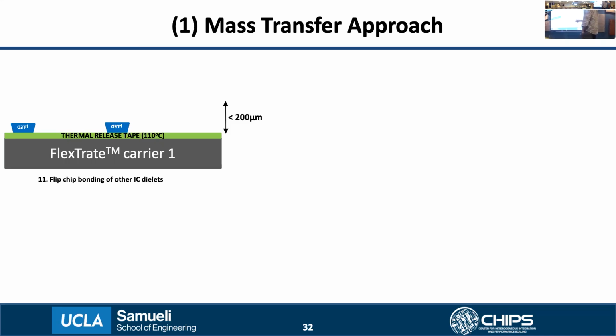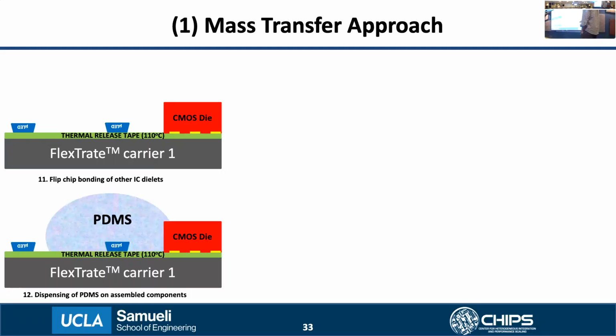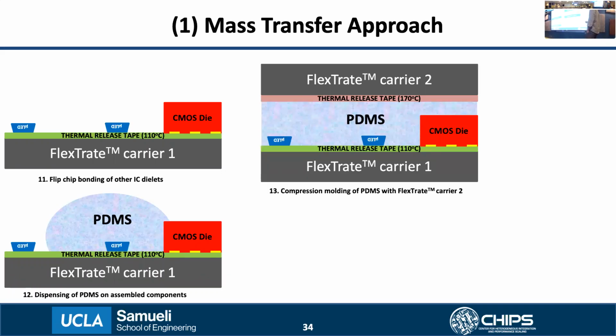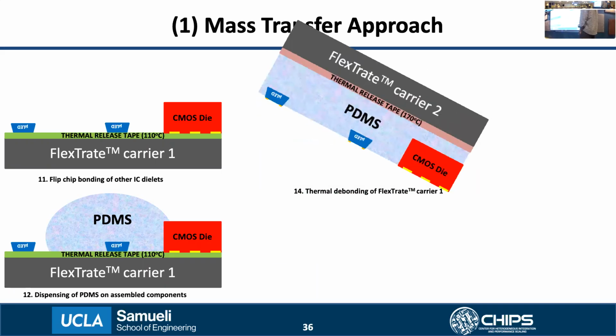And once all the LEDs have been fully assembled on the tape, we can then flip chip bond other components such as a CMOS driver die, a driver IC or a microcontroller. And then we do our fan-out process. In step 12, we dispense the PDMS, and in step 13, we compression mold the PDMS on these components using a second FlexTrate carrier with its own thermal release tape having a higher release temperature. We then thermally debond the first carrier so that we get this flat surface with the components embedded in the PDMS. And then we can do our RDL metallization using back-end line processing to define the two levels of interconnects needed to connect these components.